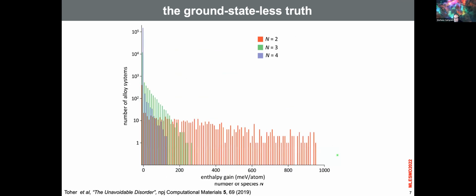So here these histograms actually show how these phase diagrams, this convex hull, gets squished. This is the histogram of the number of alloy systems with respect to the enthalpy gain. You see that for binaries it's very spread, you see that you have even 1 electron volt per atom. But once you get to the ternaries and quaternaries, everything gets squished toward zero, despite the number of configurations increasing. The number of configurations increases logarithmically, it's a log plot. So even if the number of configurations is exploding, because you have more configurations and this explodes factorially.